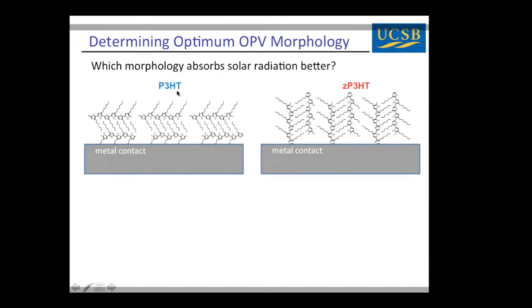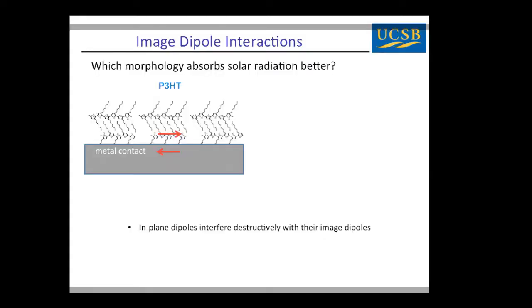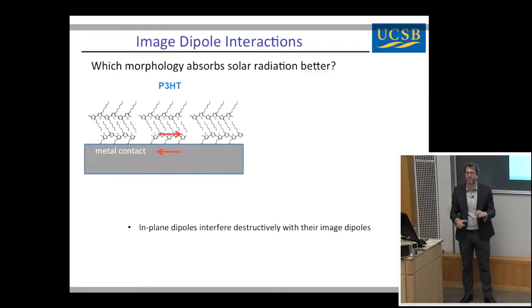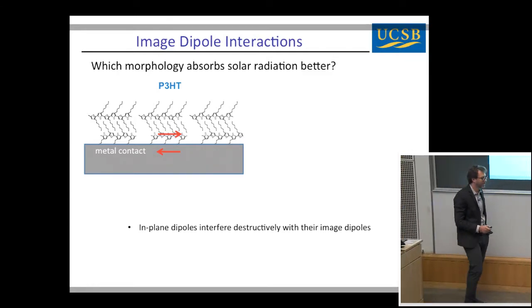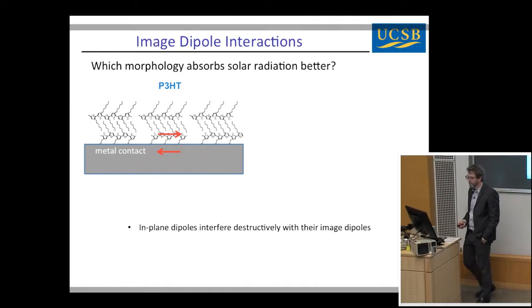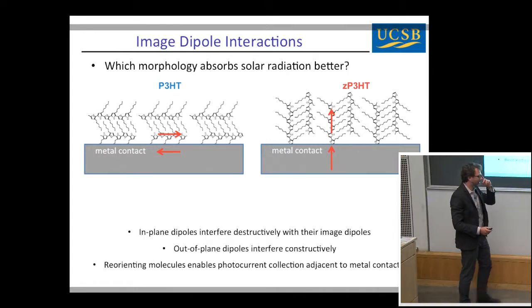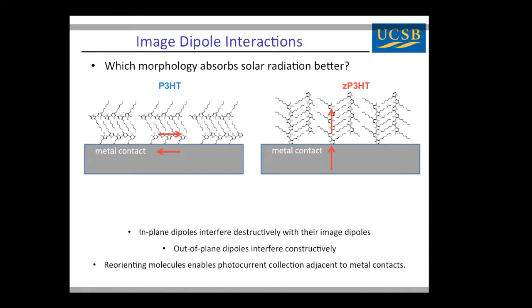Here's P3HT. Okay. Now light from the sun, so we're talking about a solar cell. So light from the sun comes with in-plane oriented E fields. So most people would think that this is clearly the better orientation. Okay. But if your molecules are sitting on a metal contact, something bad happens. Okay. The interaction of the excitons in your molecule with the metal creates an anti-parallel image dipole, and these two interfere destructively. So we get quenching of our in-plane oriented excitations for molecules sitting on a metal surface. And in contrast, this interaction is constructive or enhanced if you have a vertically oriented dipole.